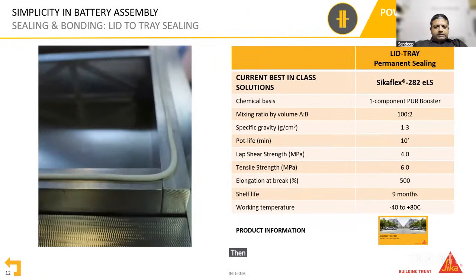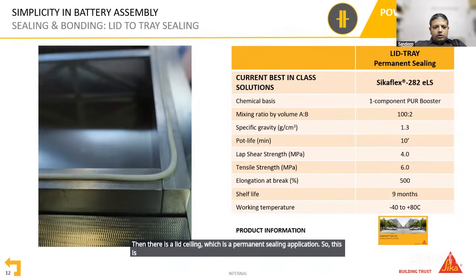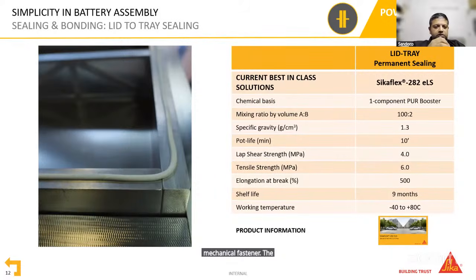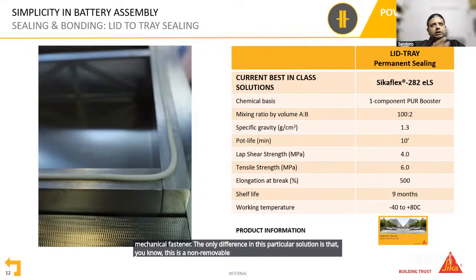Then there is a lid sealing, which is a permanent sealing application. So this is again one component polyurethane based material, which is basically used for the top lid application. A lot of people might go with an FIPG or a CIPG solution, and then a mechanical fastener. The only difference in this particular solution is that this is a non-removable bond. But quite a lot of OEMs are already using this material because a lot of people don't want the battery to be opened by a third party. In that case, you can go with a permanent bond.